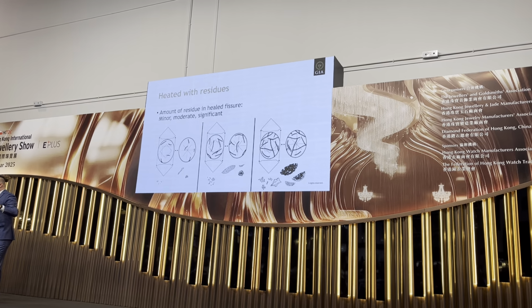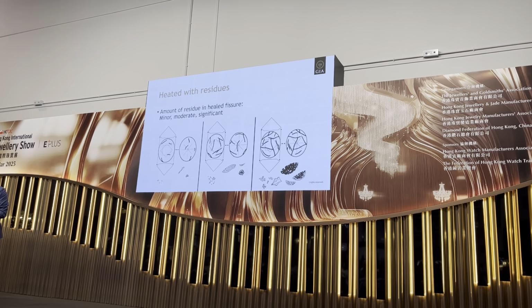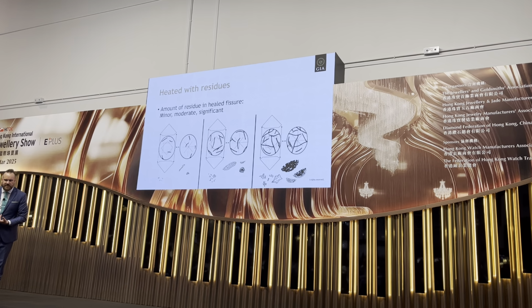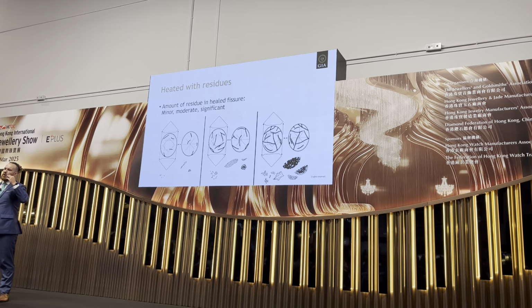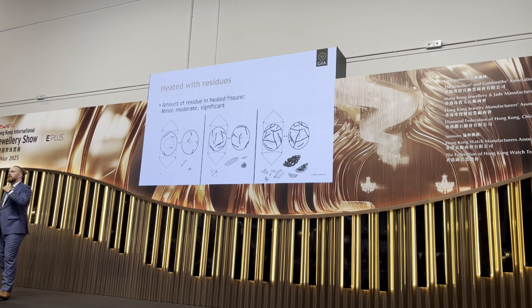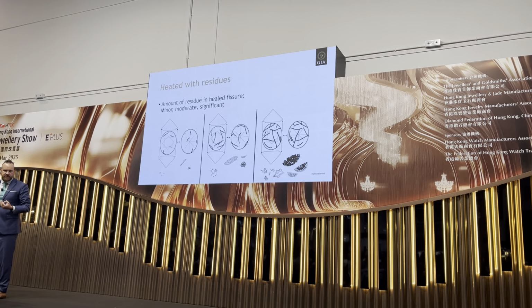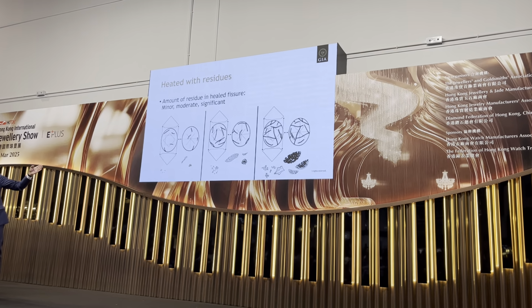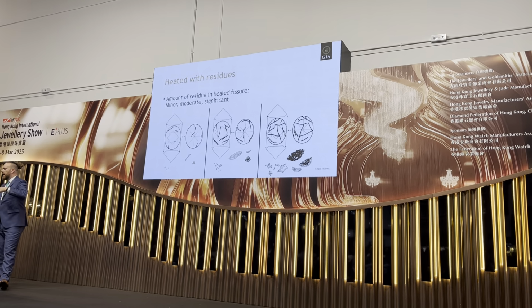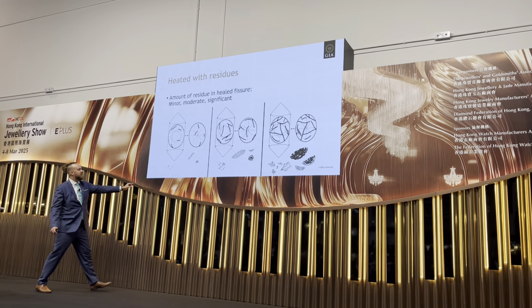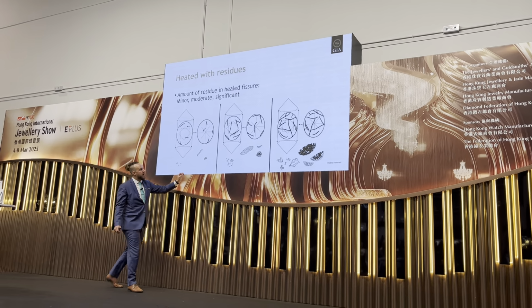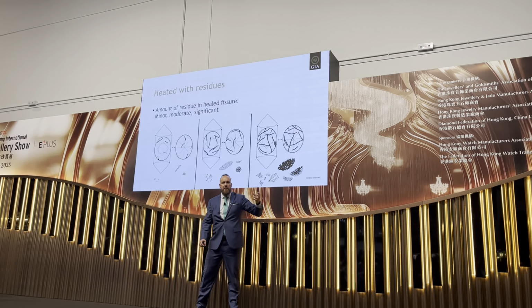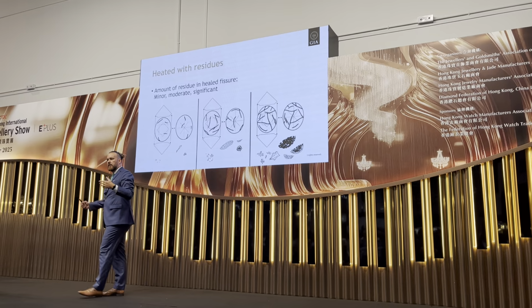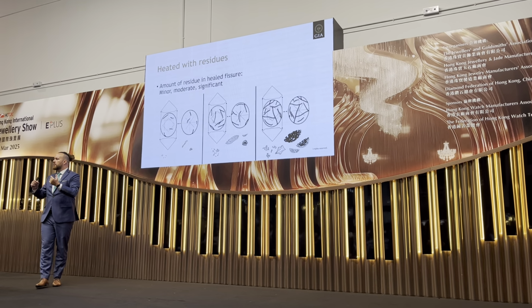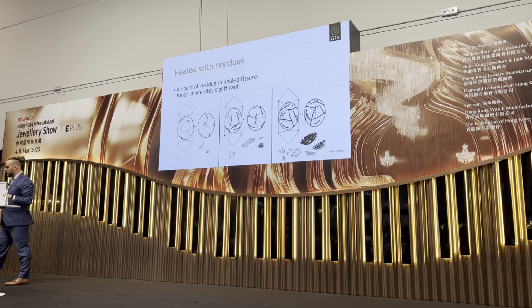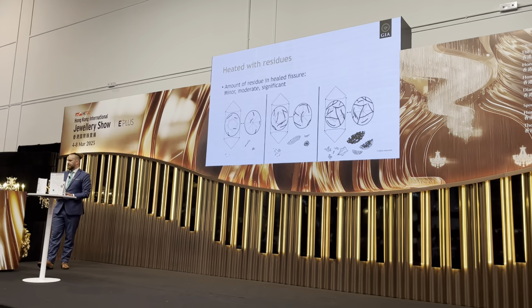That is completely healed, and we are only left with that scar where that fracture used to be. Now, of course, it matters how many of these scars we see, how many of these healed fractures we see. Because same thing as with emerald, if there's only one fracture that used to be healed, that material is much rarer than one with 100 fractures that have been healed. So we use the same classification there, that minor, moderate, significant. And you can see some visual examples here, where here there is some very subtle scarring, but on the right we can see the scar is very big, very coarse. There's a lot of them out there. So that's the difference between that minor, moderate, and significant residue in your fractures of your heated ruby.